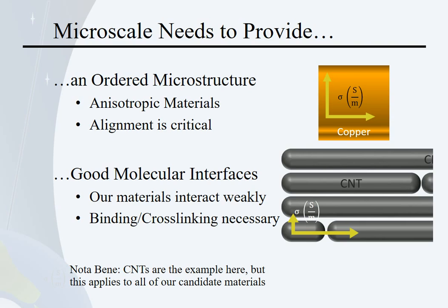If I then measure conductivity from the top face to the bottom face, I should get about that same value for conductivity. This is not true for our nanotubes. They're much better conductors along the long axis than they are across the short one. We see the same thing for strength. We see the reverse for local attraction. The side walls are much more attractive to each other than the end caps are, and so on and so forth. So order is important. I want to emphasize exactly how anisotropic our materials are.